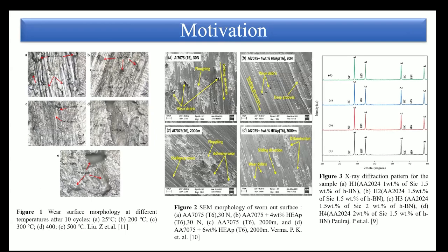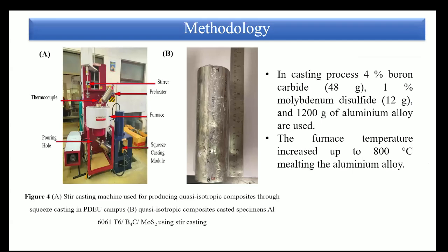Our aim is to cast the quasi-isotropic material. This stir casting machine is used for producing the quasi-isotropic composite through squeeze casting. In this casting, we choose aluminum 6061 reinforced with boron carbide and molybdenum disulfide for the stir casting. In the casting process, 4% boron carbide and 1% molybdenum disulfide are used, with 1200 grams of aluminum.